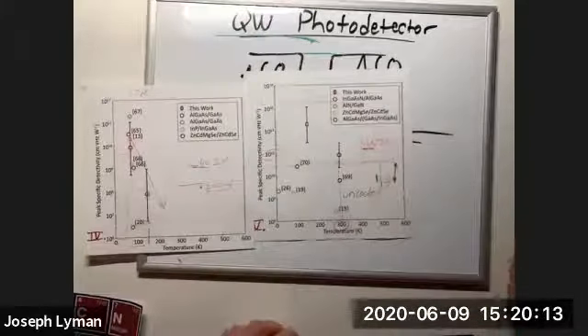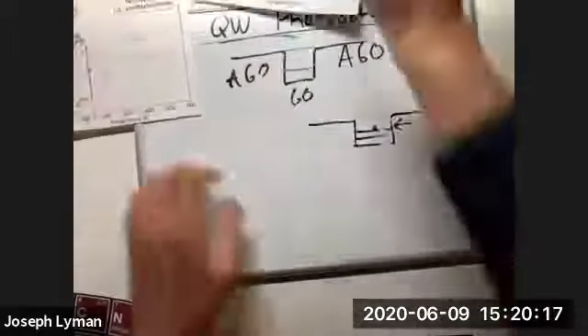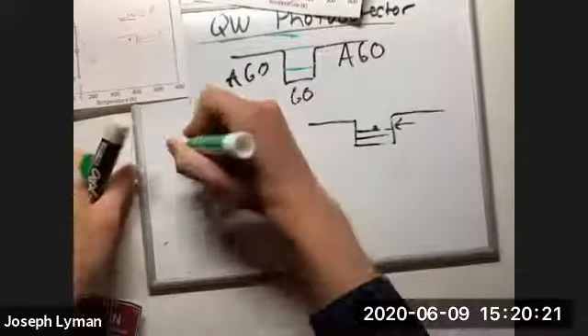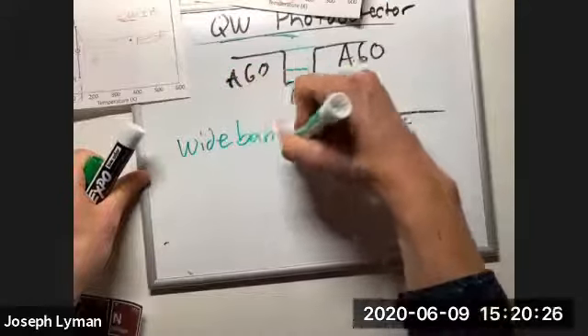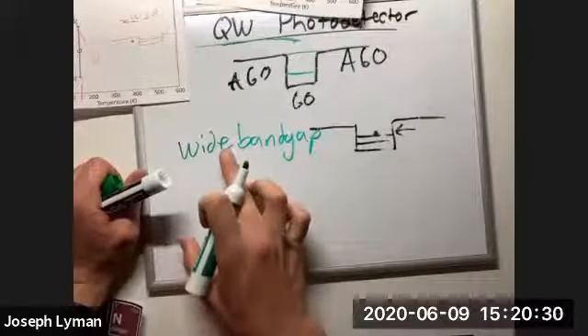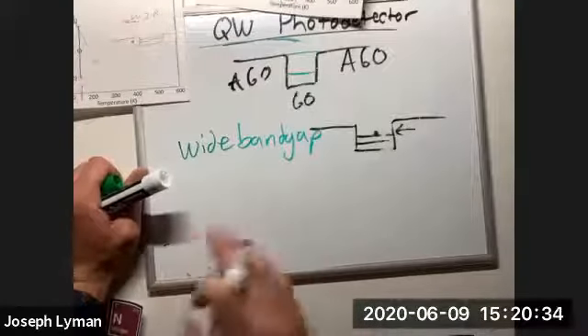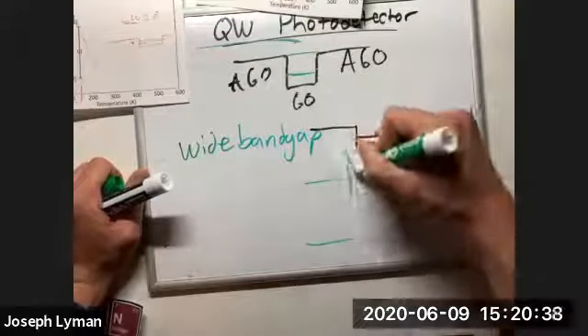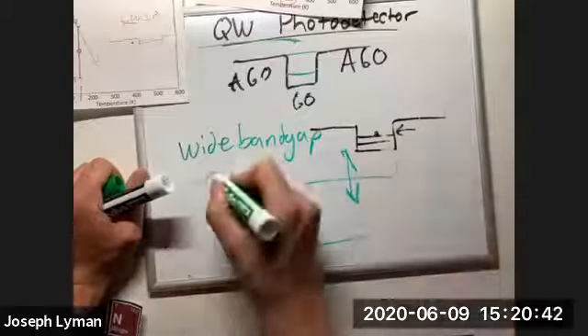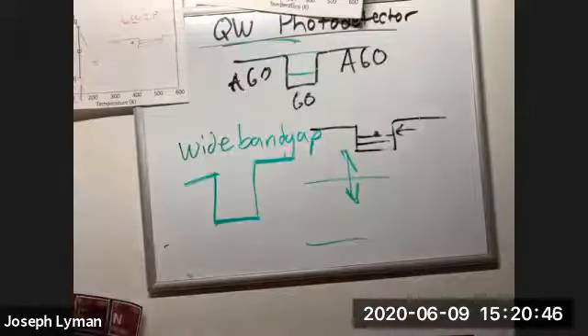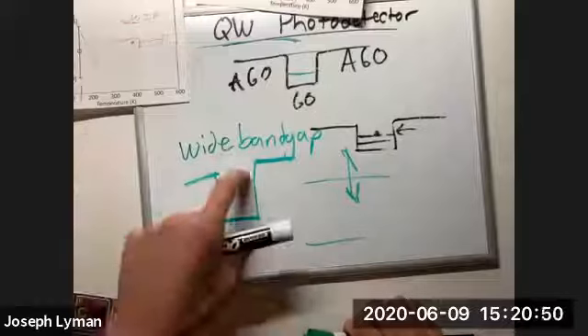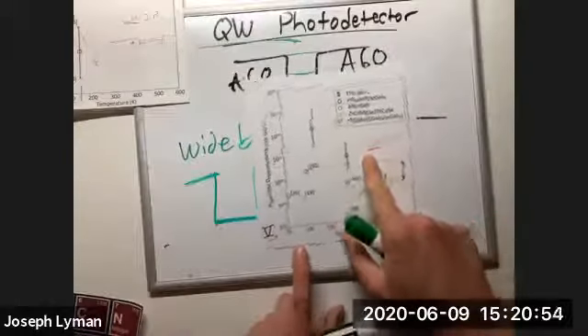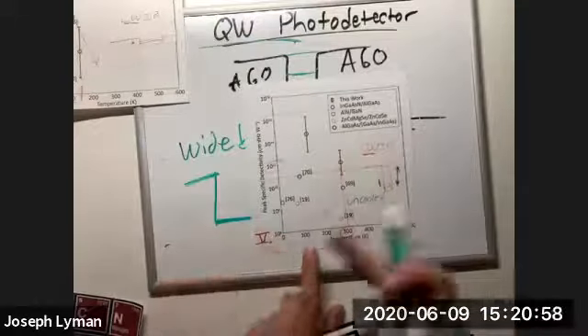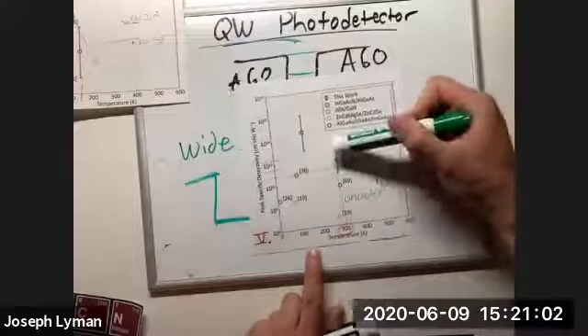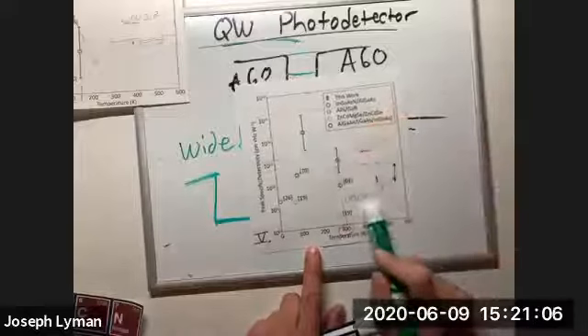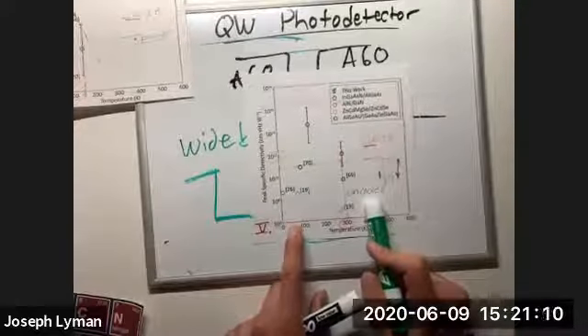This is because gallium oxide is called a wide bandgap semiconductor. Wide bandgap basically means that the energy required to break bonds in the crystal is quite high compared to something like silicon. And it means there's a lot of room to adjust this energy level. That's why we can achieve such deep wells, because it's a wide bandgap semiconductor. By alloying it with aluminum, we're able to make the well significantly deep. We're able to access shorter wavelengths than are achieved with conventional materials. And because of this, we're showing that at room temperature, you could achieve performance that is quite impressive, and it's not even required to be cooled to liquid helium or liquid nitrogen temperatures.